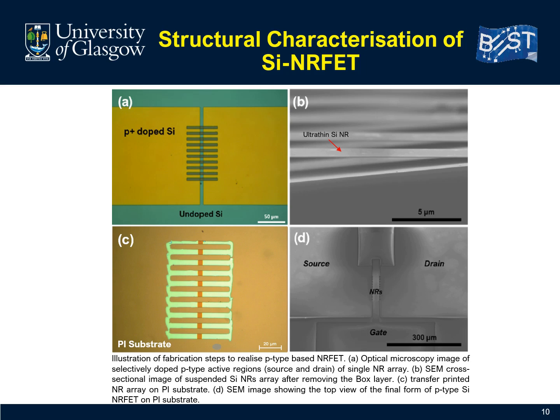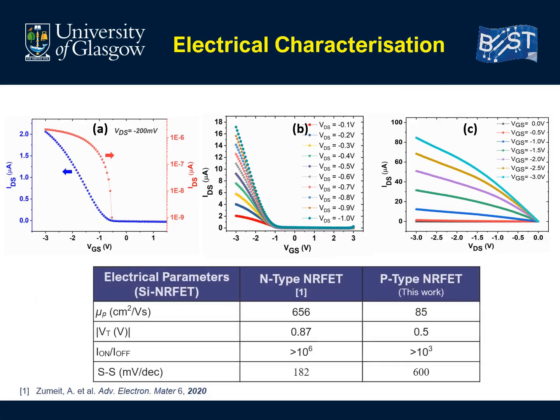In terms of the electrical characterization of the presented p-type silicon nanoribbon-based transistor, the electrical characteristics of the final device with the drain bias of minus 200 millivolt are shown in figure A. The current on and off ratio was found to be around 10 to the power 3. The extracted subthreshold swing is around 600 millivolt per decade. Figure B shows the transfer characteristics at different values of drain to source voltage. It's worthy to note that the threshold voltage VTH remains constant even when the VDS is changed. That shows the high stability behavior.